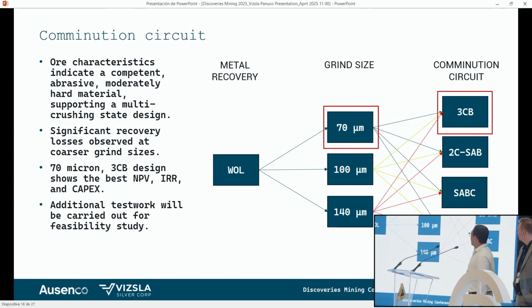So now with the comminution circuit, now that we have the silver recovery in place, we can run scenarios on how much we need to grind the ore. There were also some trade-off studies conducted, and we have the whole ore leach sample, and we tried 3 scenarios. We have a recovery model for 3 scenarios: one at 70 microns, one at 100 microns, and one at 140 microns. For each of these scenarios, we ran an economic model to see which provided the lowest capex and opex for reducing to the optimum grind size.